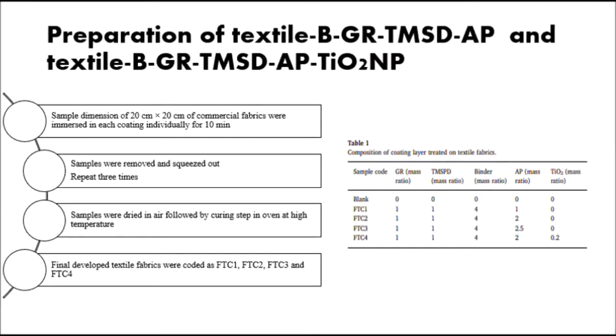For the preparation of textile, sample dimension of 20 cm by 20 cm of commercial fabrics were immersed in each coating individually for 10 minutes. The samples were then removed and squeezed out. This process was repeated 3 times. And then afterwards, the samples were dried in air, followed by the curing step in an oven at high temperature.